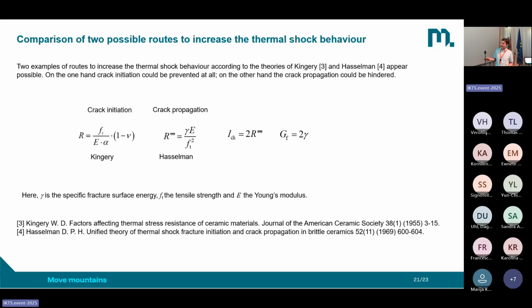And what is my idea behind it? I make a relation between the elastic strain. So R represents a temperature difference in a plate. Alpha here is the thermal expansion. So if I then multiply R with alpha, then I have here the thermal expansion. And on the right-hand side, I have the tensile strength divided by the Young's modulus, which is the fracture strain. So he says, okay, if my thermal expansion equals the fracture strain, then I have fracture, and this I would like to avoid. So it's about the strain.